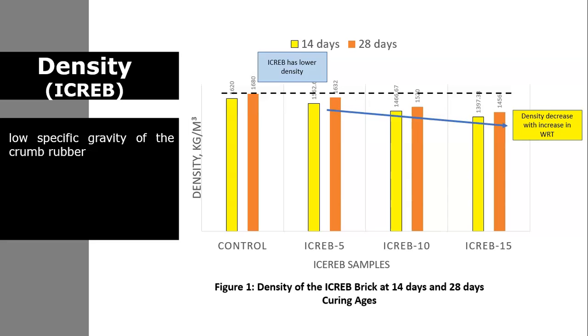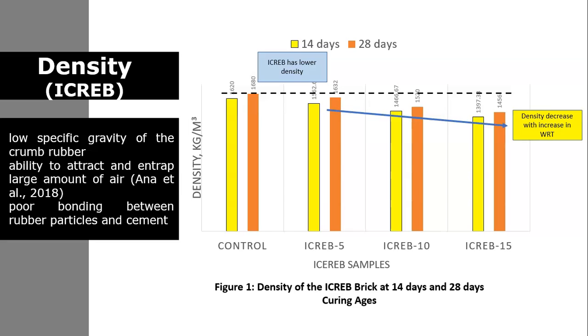When added into the mixtures, an increase in the rubber content will increase the air content, which in turn will reduce the unit weight of the brick samples. Another reason is possibly its non-polar nature, where the rubber particles have the ability to attract and entrap a large amount of air, thus reducing the density of the specimen. In addition, the poor bonding between rubber particles and cement also creates voids, thus increasing the brick volume and also resulting in density reduction.